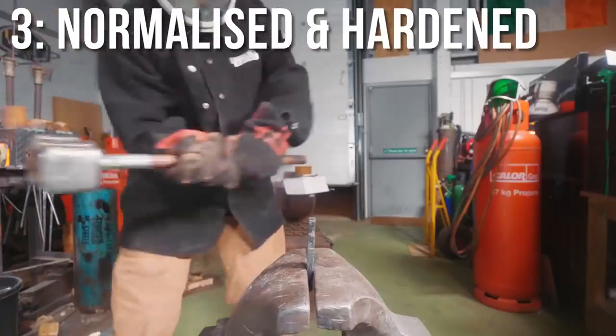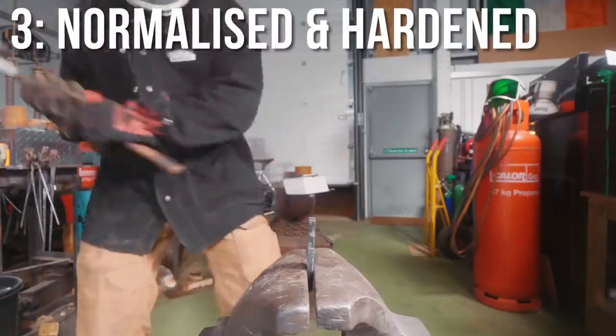Next we tested our quench hardened sample, which is stupid and dangerous and should not be tried at home. This fractured explosively and tore a hole through Alex's reflector. Finally we tested the tempered material, which absorbed every hammer blow with minimal plastic deformation and only broke when we cut a notch into the material to create a stress concentration point. This material is tough, capable of absorbing energy without deforming permanently, and hard, allowing it to resist damage to the cutting edge. It is the ideal material for a blade.